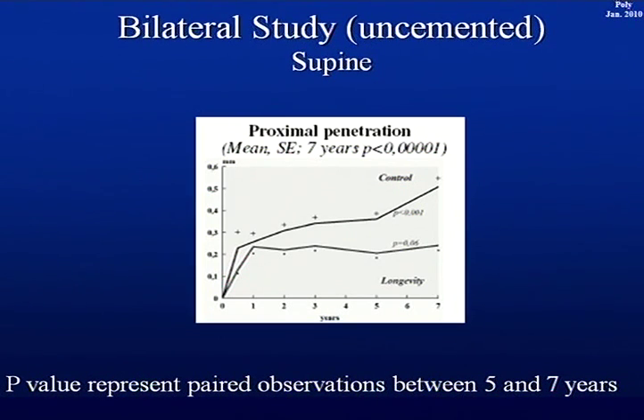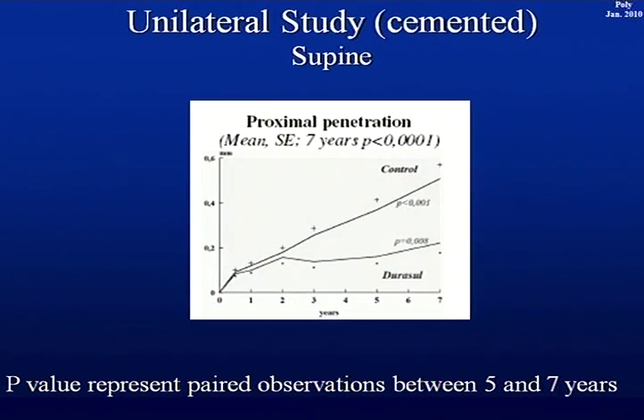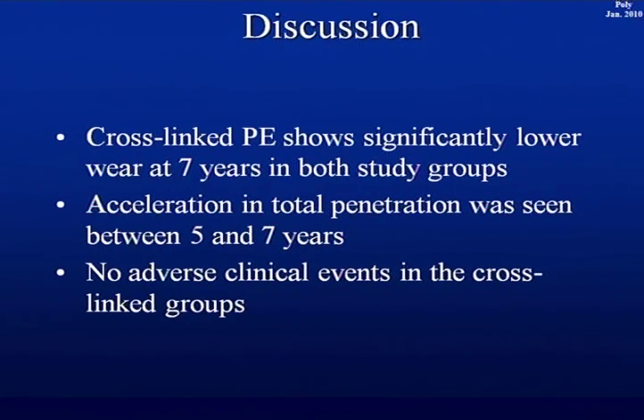That's how highly cross-linked should perform. But the disturbing issue, and this is a scan image for the recent OIS meeting, that they did see a shift between 5 and 7 years, increased head penetration, presumably where? And the same in the cemented study. So significantly lower cross-linked wear at 7 in both study groups, but an acceleration of total penetration between 5 and 7, and still no adverse clinical events as such in the cross-linked groups.